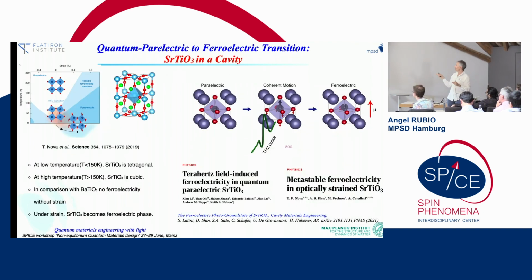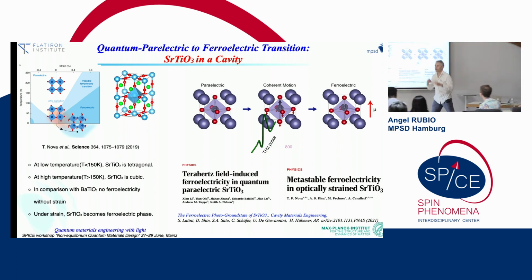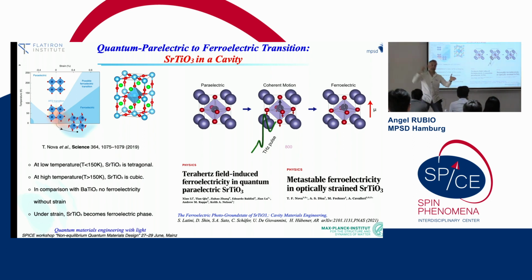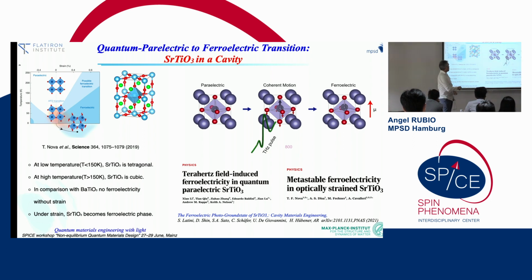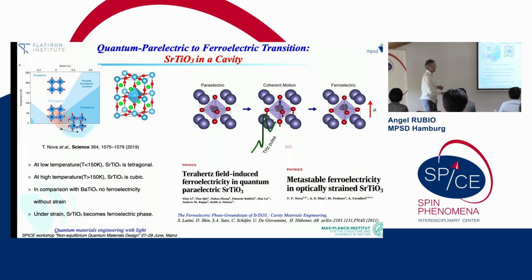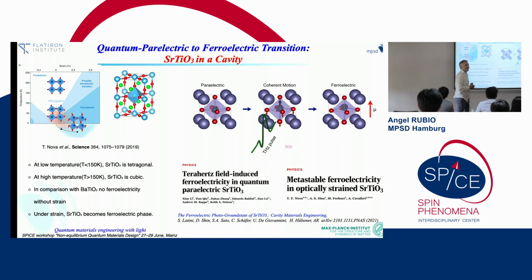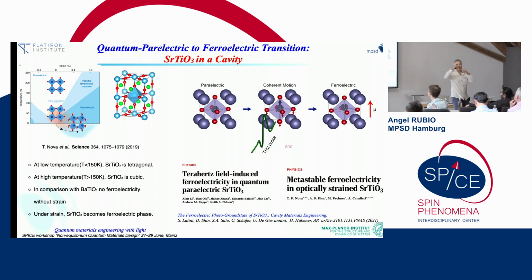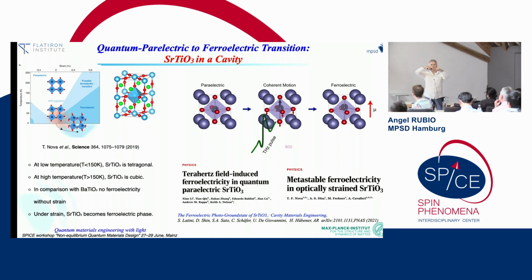I'm not going to show you the results, but this is work that I presented already in the past. In STO it is known that if you drive the system, this was done by Andrea and also the Keith Nelson group, you drive the soft phonon mode, which is the TO mode, and you can induce a paraelectric to ferroelectric transition. Depending on how you do it, the lifetime of this ferroelectric transition that you generate is longer or shorter. In the case of Keith Nelson, the ferroelectricity lives only while you are pumping, not much longer. However, the idea is that you have this strongly fluctuating dipole, which is the TO mode, that gives you the transition.